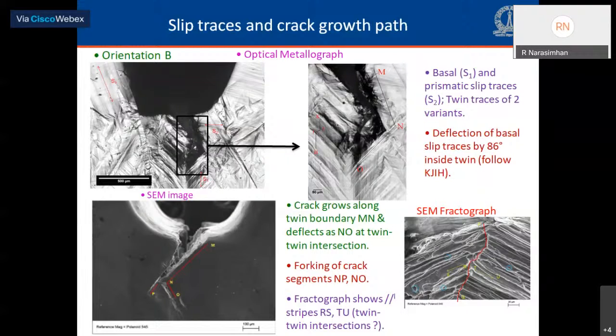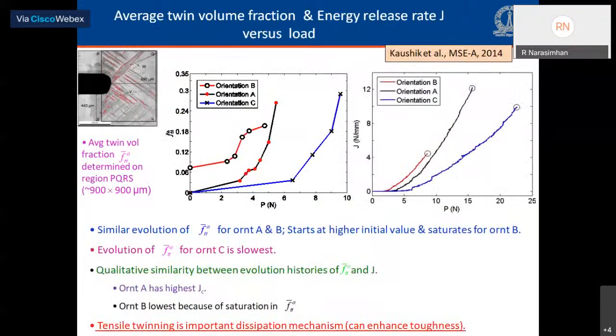The bottom right side image is an SEM fractograph, and we see very intriguing features of some elongated stripes. Like I marked some of them as RS and TU, we believe that these are due to intersections of twins of the other variant on the fracture surface. We sought the twin-twin intersection in the optical metallographs as well as in the EBSD images.